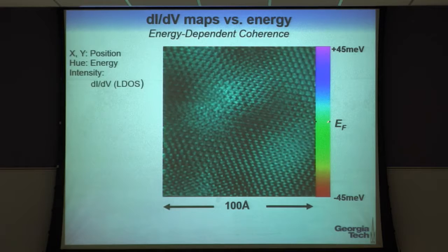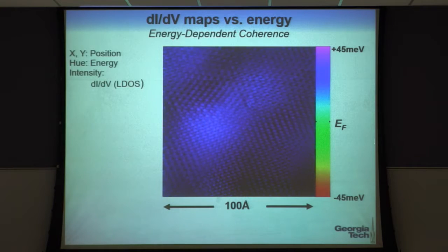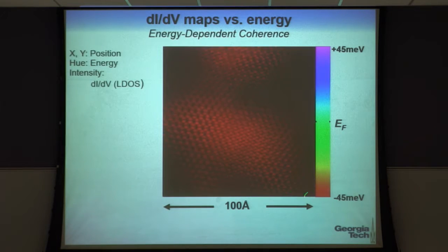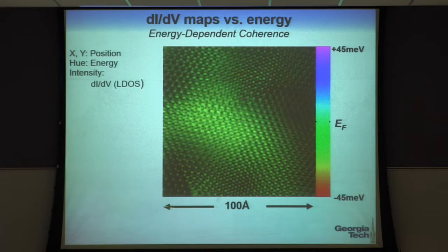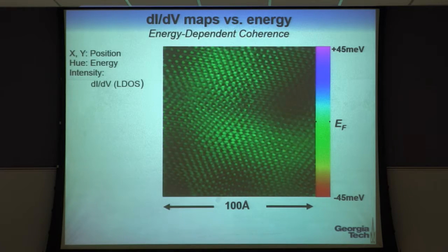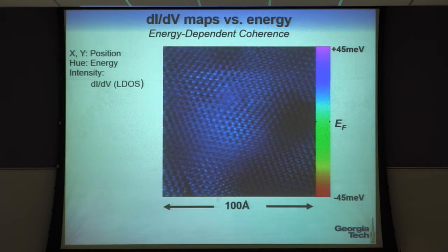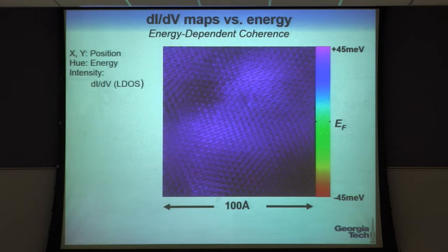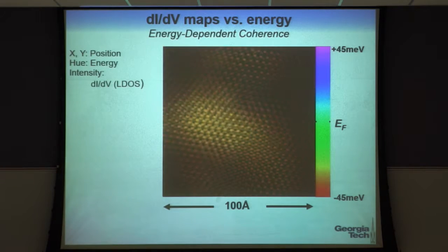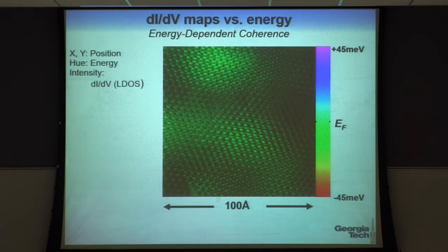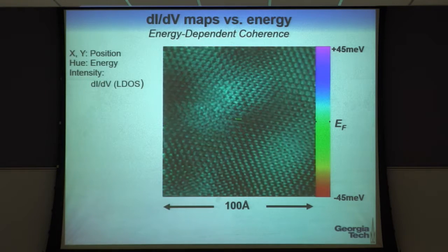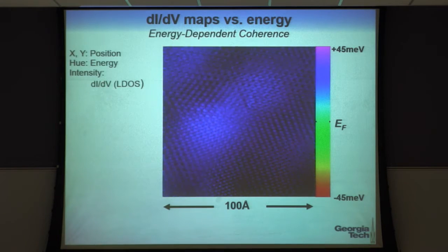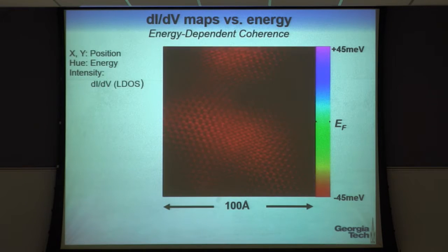It's crossing the Fermi energy around now, and then goes back up to high energy, and it's going to start over again down here. What you're looking at is a 100 by 100 angstrom area, and these are slices at different energies. So this is psi squared, the wave function squared, or the electron density as a function of position across the surface. And all these dark things moving around, that's the nodal structure of those waves scattering on the surface,